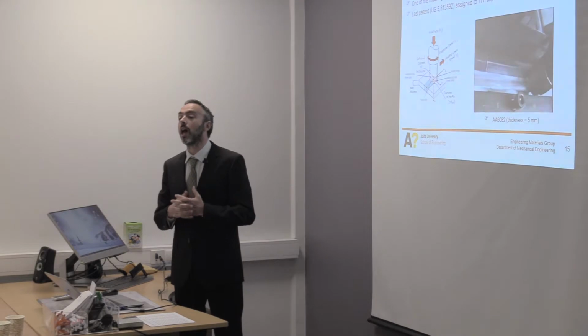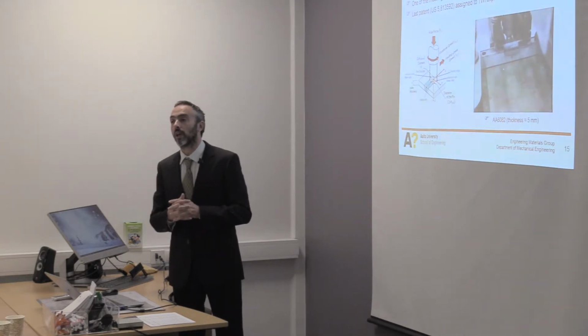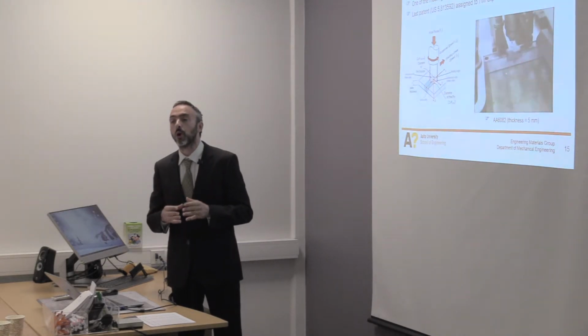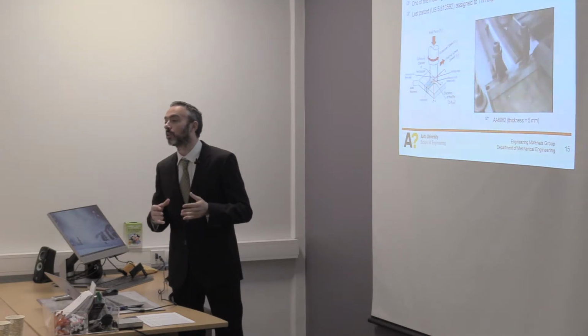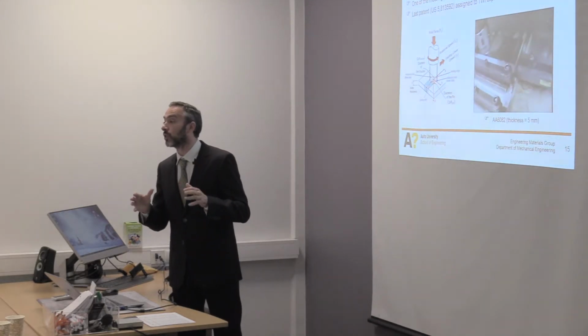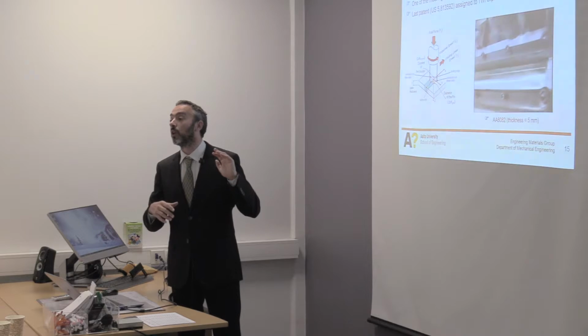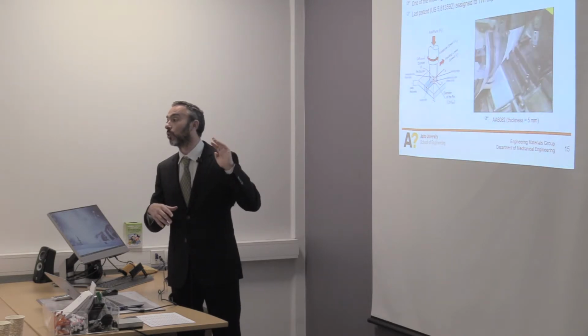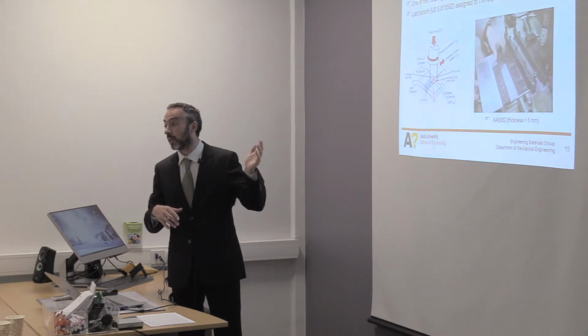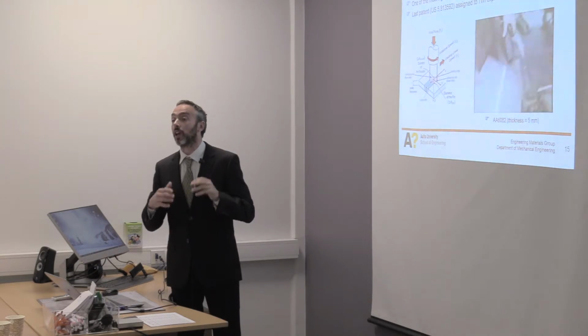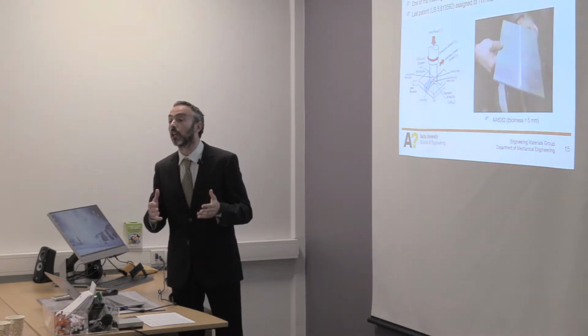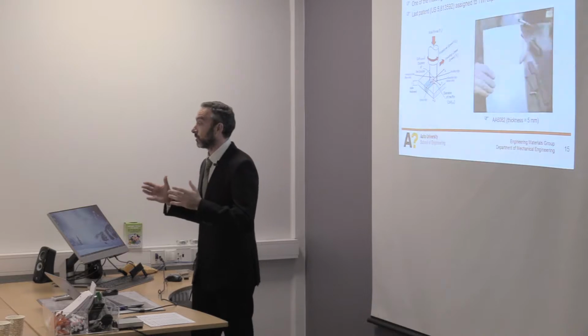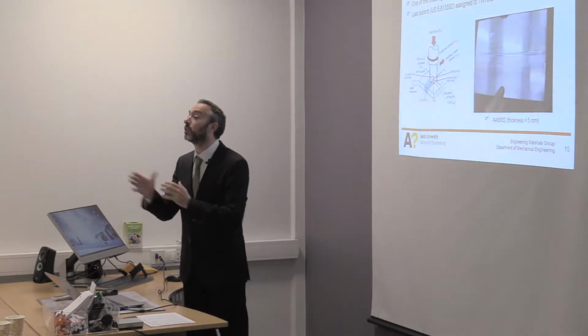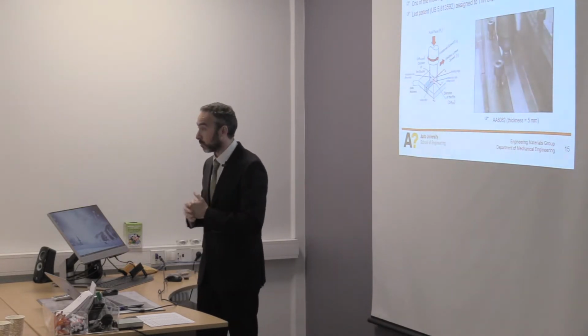So we have a non-consumable tool that has a shoulder and a probe. The probe promotes the stirring of the material because there is no need for preparation, and as you see, there is no emission of radiation or no need of filler metals or shielding gases. Okay? We reach very high performance. The material is thermomechanically processed, is forged as the best materials, as the base materials are operated and produced.